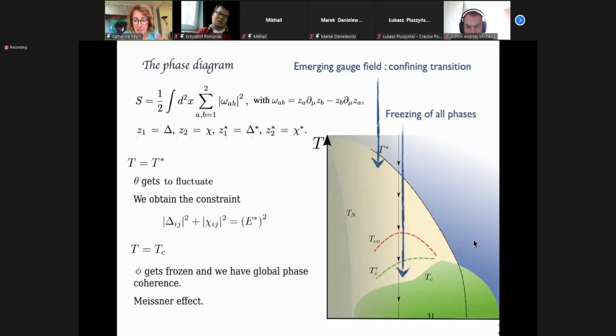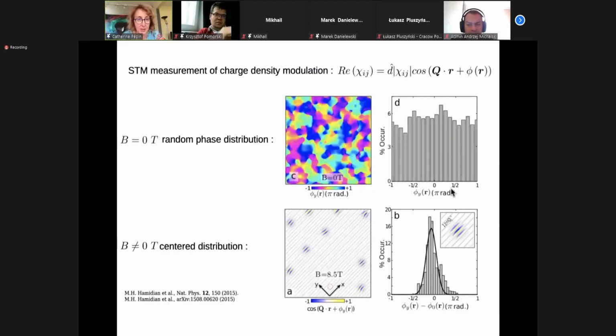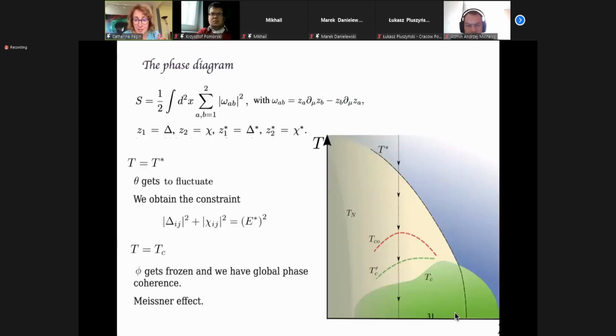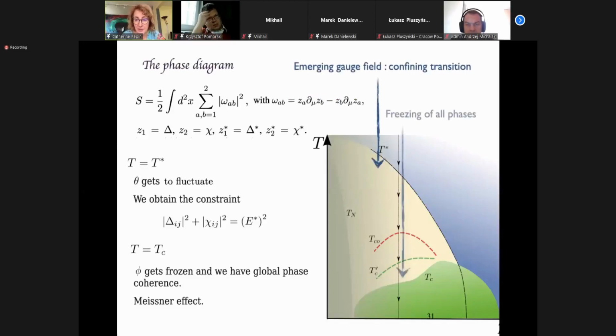And below Tc, when we have the first real long-range order, all the phases freeze. And on the right-hand side, in the strange metal phase of the cuprates, we will get incoherent bosons. We'll come back to it. So by an elementary idea, we get this experiment for free with this idea. Namely, below Tc, the phases of the two orders freeze.